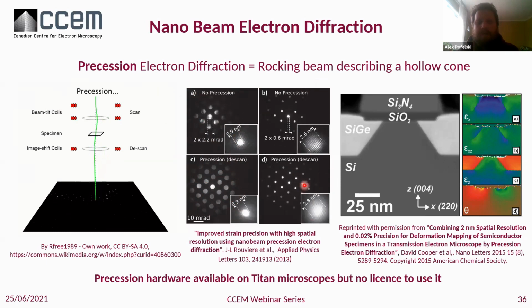The same thing can be applied in this microprobe mode, with a little less convergence. So it's probably still nanoprobe. I'm not totally sure about this experimental condition because the resolution is slightly small. But the idea is to say that the precession is not degrading the resolution. And on the right, you have this wonderful map. This work has been done at CEA Grenoble. They are using a Titan microscope to do this experiment. And here, this is combining 2 nanometer resolution with 0.02% precision, so the sensitivity. You can see how gorgeous those strain maps are. And this is combining this effect of precession with the strength of a processing method to look at those disks.